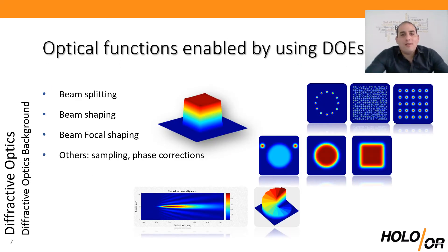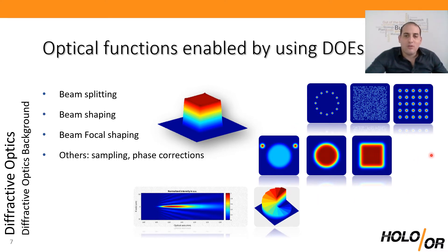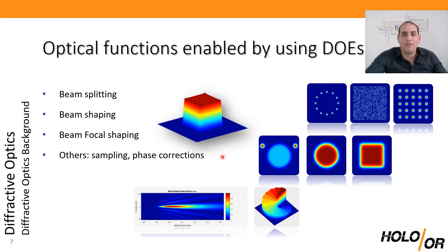With DOEs you can shape the light into whatever you want. You can shape it into a flat top — a square flat top, a round flat top, a rectangle, a line — whatever fits the process parameters. You can even make complex shapes such as a brazing shape, where you have two hot spots on the sides of the brazing on galvanized sheets and a central spot melting the brazing wire, giving you cleaning and preheating of the two sides before brazing them together. You can also split the spots, enabling higher throughput and power spread for applications such as drilling.